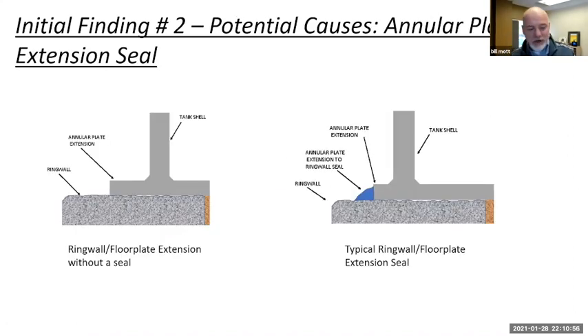This is supposed to represent what that area looks like, where the tank shell rests on the annular plate. It's welded to the annular plate here, the floor plate extension or annular plate extension, and that rests on a concrete ring wall. The ring wall was existing. There's no bond between the plate and the concrete. So any water that pools on that will either slide off the side of the ring wall, or it will migrate and seep beneath the tank in between the secondary containment and the floor plate. Most operators try to avoid that, and they install a flexible grout to seal that area, not unlike what you would put around your bathroom tub or around your windows at home.